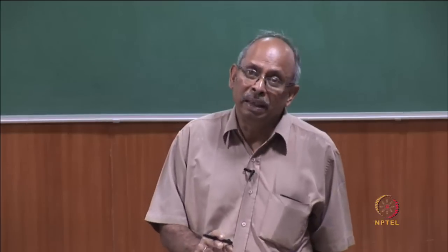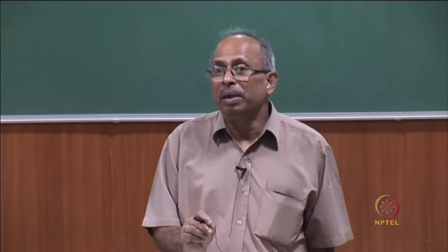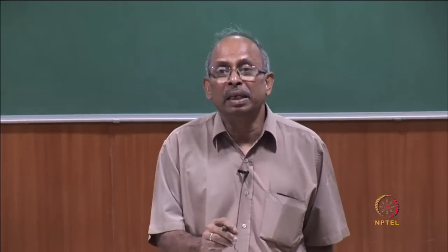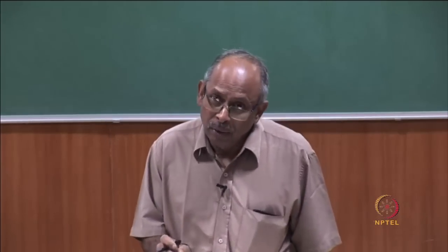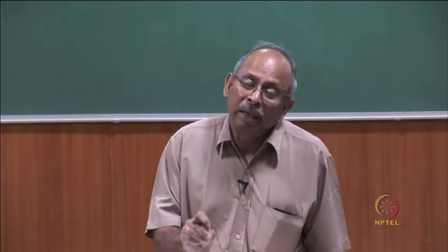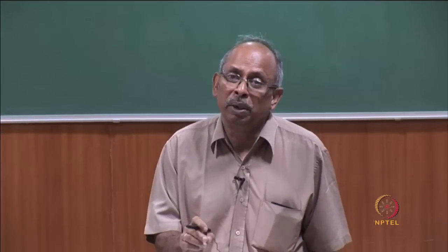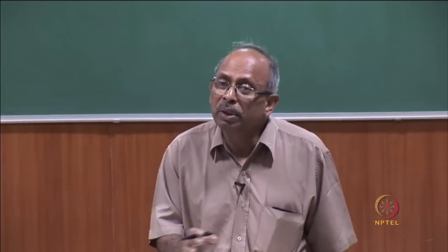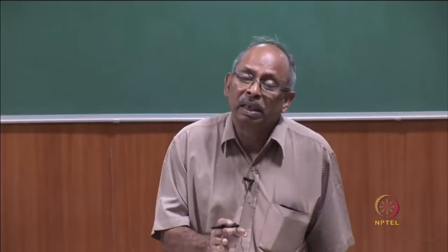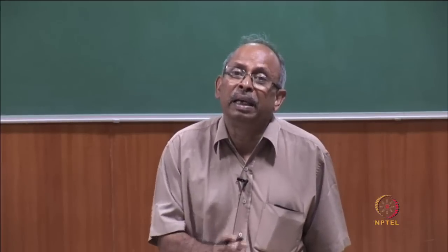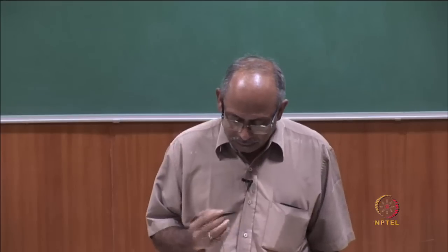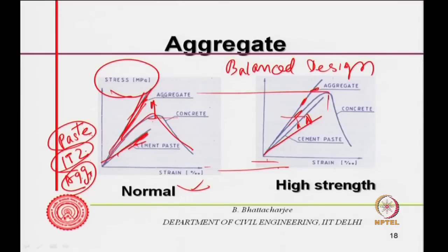By improving the ITZ through fine material, pozzolanic material which can get inside, and water reducing agent which will disperse the particles and allow finer material to get into the interstices of those cementitious particles, both at the interface of the aggregate system at the ITZ as well, and improve the porosity and refine the pores. So, that is the principle of high strength concrete.